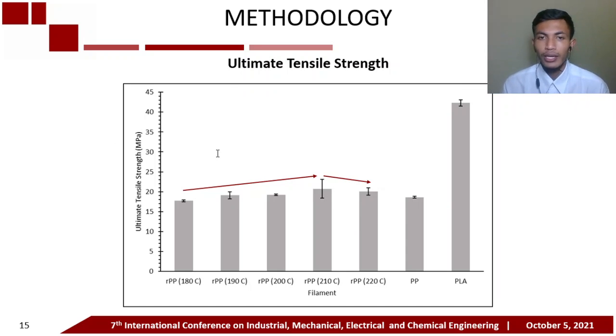The data shows that the highest ultimate strength value is at 210 Celsius. When the temperature goes from 180 Celsius to 210 Celsius, it appears that the tensile value increases with the addition of nozzle temperature, then decreases when it reaches 220 Celsius. Based on this phenomenon, we can conclude a hypothesis that the operating temperature of the RPP filament is at 210 Celsius.